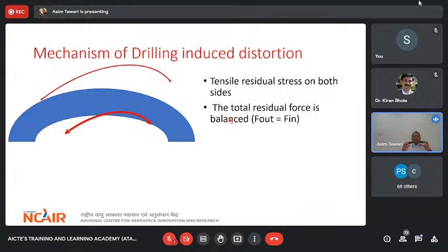And in the initial case, they are both balancing each other. So the residual stress outside in the periphery of that pipe and the residual stress inside the periphery are exactly balancing each other. Why are they balancing each other? Because it's a residual stress. There's no external stress, right? So they have to balance each other out. And since they balance each other out, there is no distortion. It just remains like that.